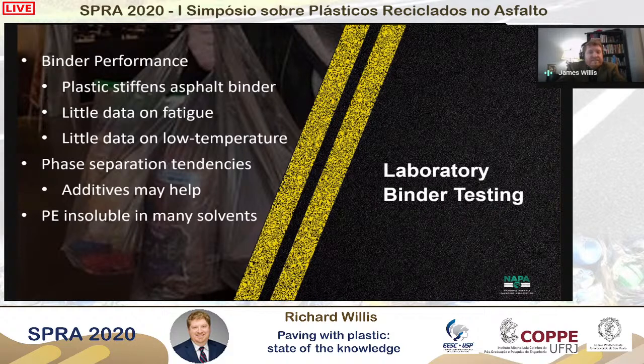The overall consistent finding was that the use of recycled materials reduced the penetration and ductility, and increased the softening point, viscosity, and the high temperature performance grade. Therefore, you're going to improve the rutting resistance of the mix. However, other than the reduced ductility, few studies looked at the fatigue or low temperature performance.